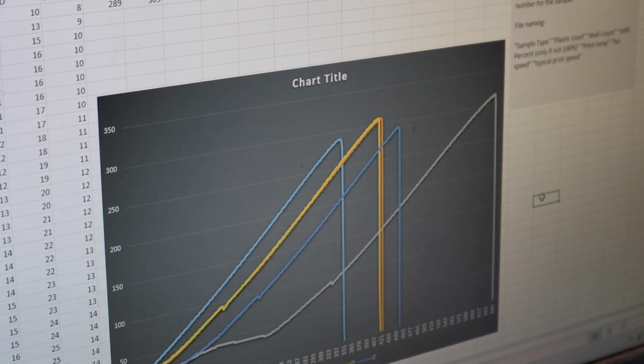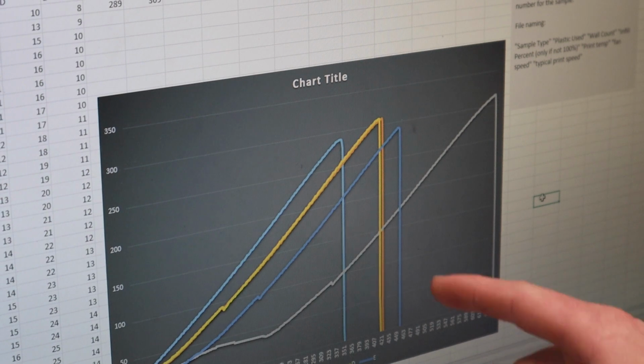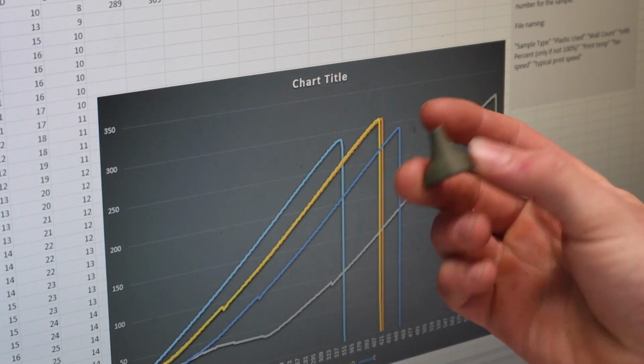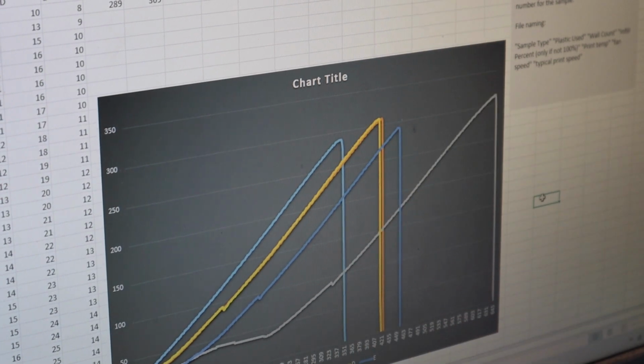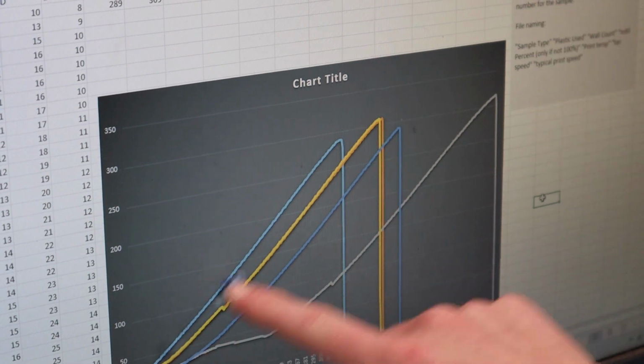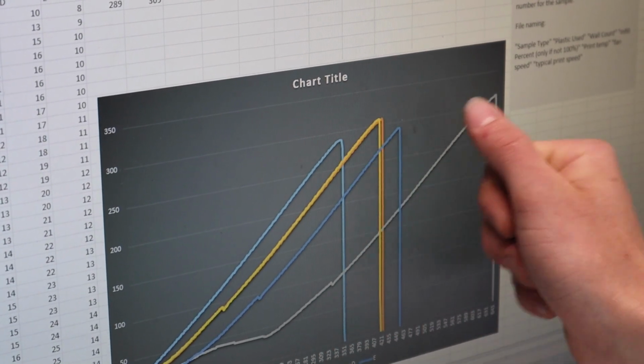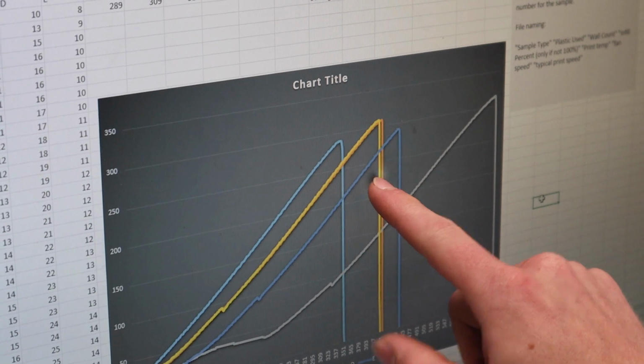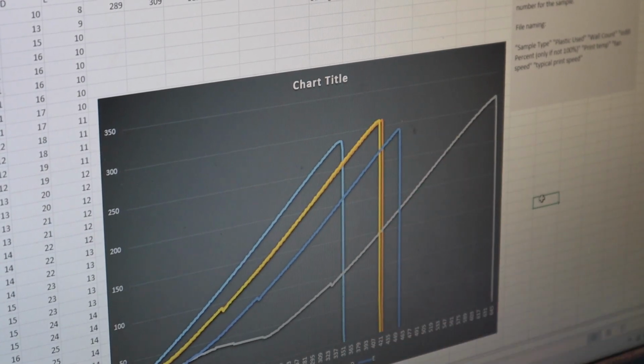Okay, so here's the results from the test with the vertical test samples, these little fellows, and we only got about 6,000 PSI tensile strength, which is not the best compared to what we did today, but it's actually still pretty good. And you can see the chart right here. We did not have any yield at all. The parts just snapped right off. This is true for almost every single FDM material out there.